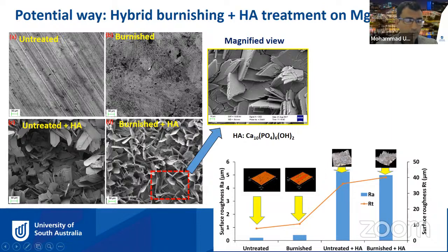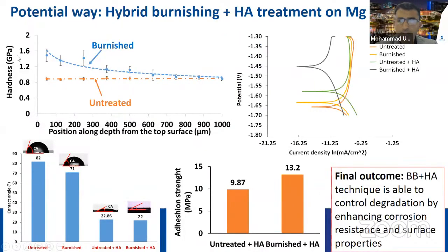And we also did some sort of roughness analysis. We found that, of course, by applying the coating on top of the burnished surface, the surface becomes rough. As you can see, the coated surface looks pretty rough here. We did some hardness measurements.